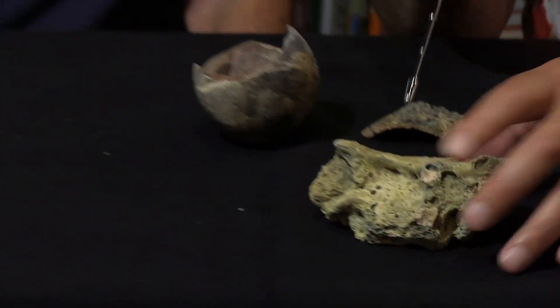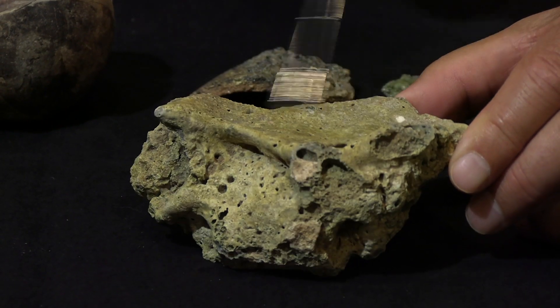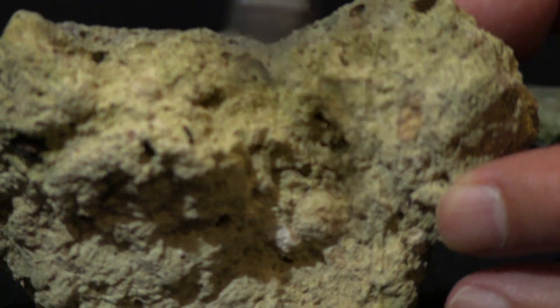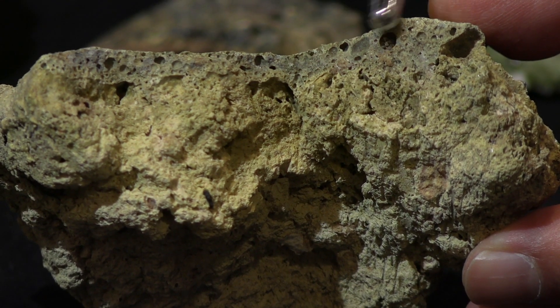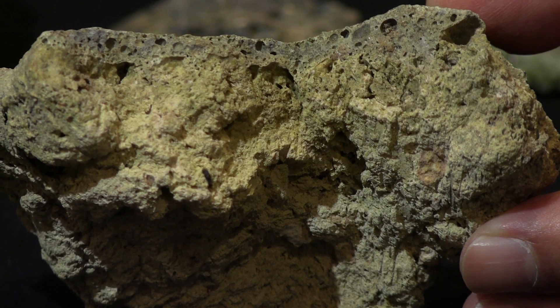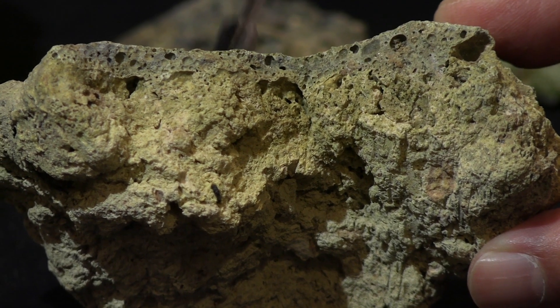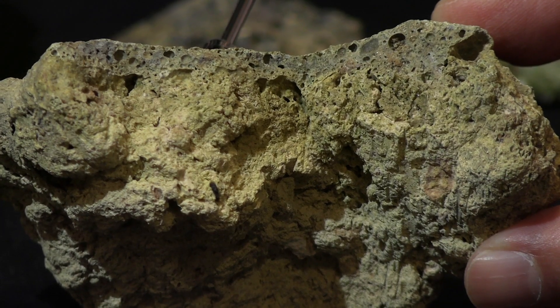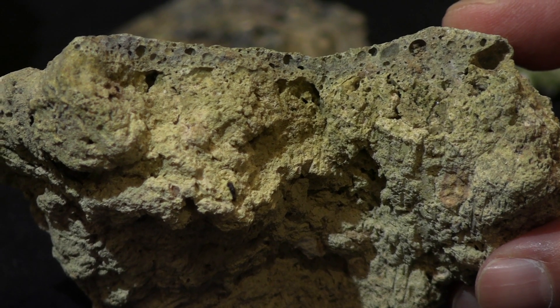This piece of mud brick — it's a mud brick fragment — look how it's melted. This is greenish glassy material. It's melted; you can see the bubbles, the outgassing of melted material. There's a surface melt only about a quarter inch deep with little bubbles. This thing got really hot. We think this was one of the bricks that got maximum exposure by being part of the upper parapets of the palace. All of these things are found mixed into the matrix — a churning, broiling, boiling matrix of destruction.